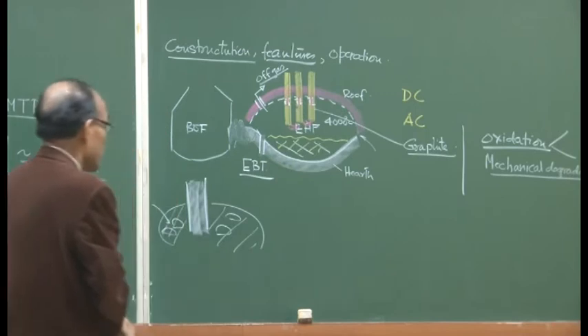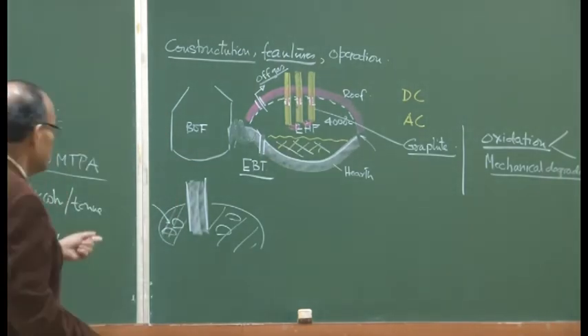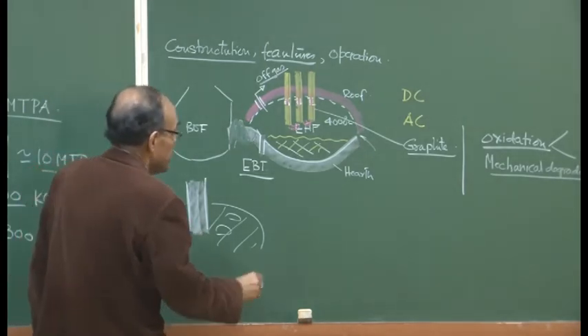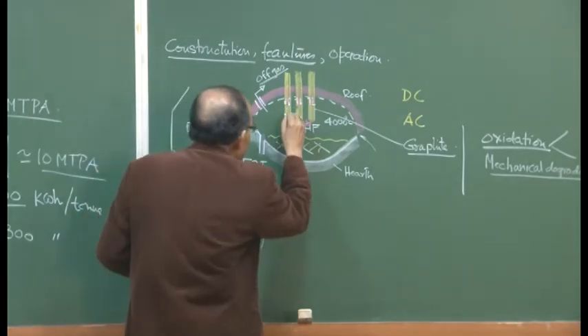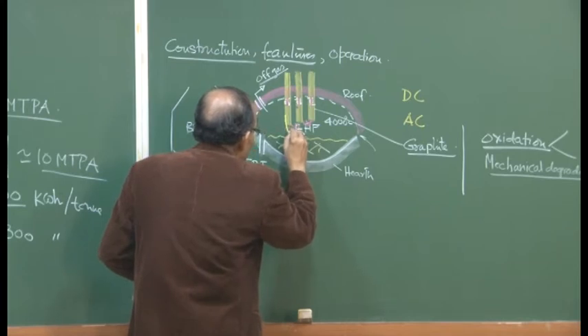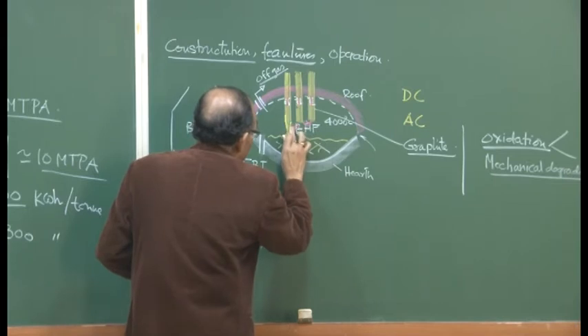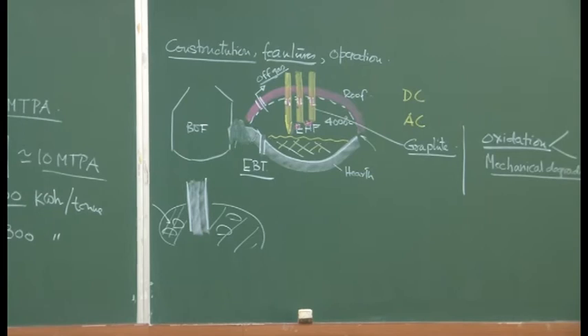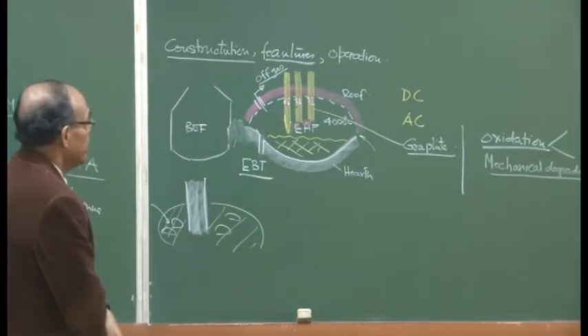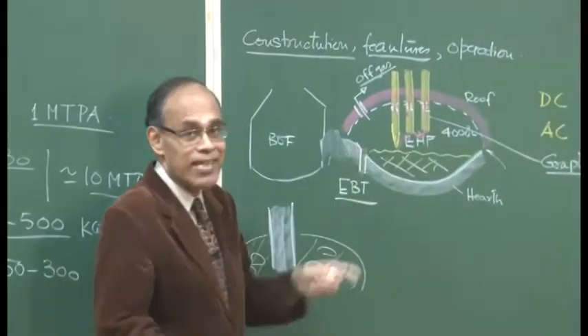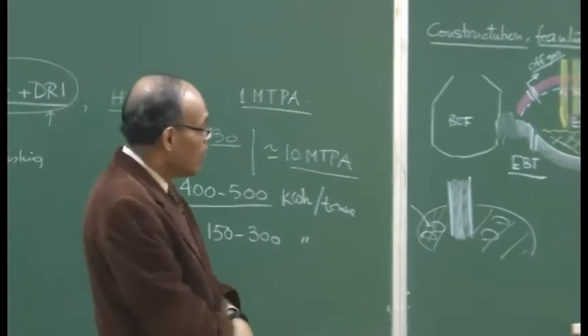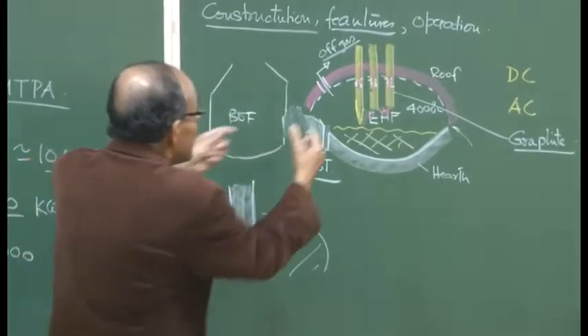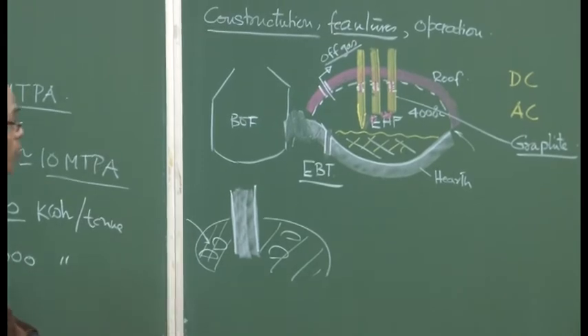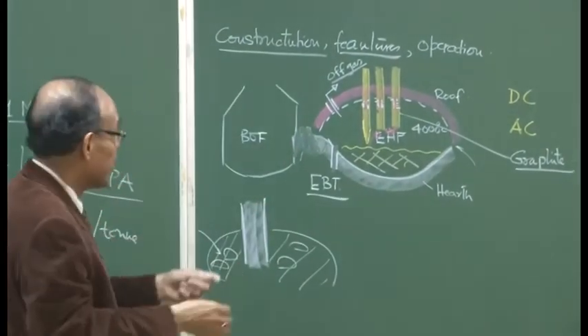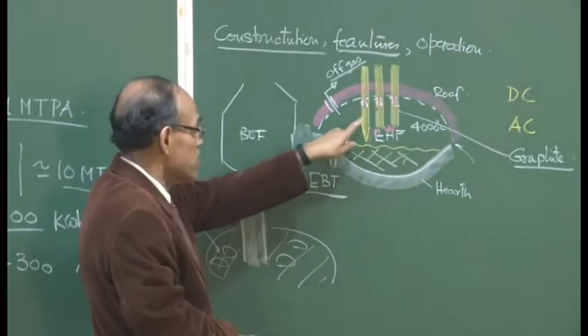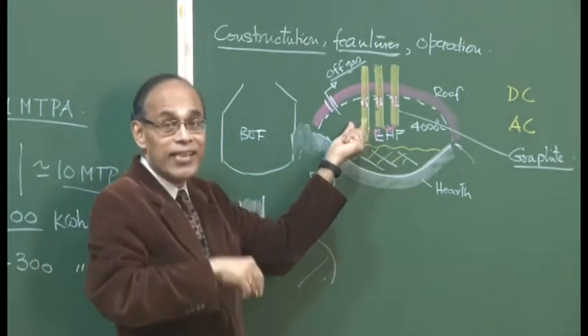Wear and tear during the handling and so on. And you can see that basically this tip will happen something like this. This is the kind of shape that the electrode is going to take after some time of operation, because this is the part which has been exposed. The diameter of the electrode as well as the current density are two important parameters in this particular case, which control the amount of heat which is going to be developed in the electrode itself, what is the kind of erosion, what is the kind of electric heating efficiency. And as I said, the two important parameters to this end are basically the diameter of the electrode and the current density that you apply.